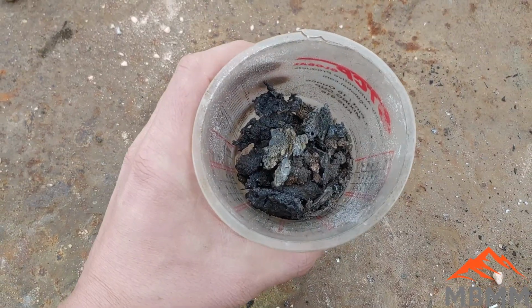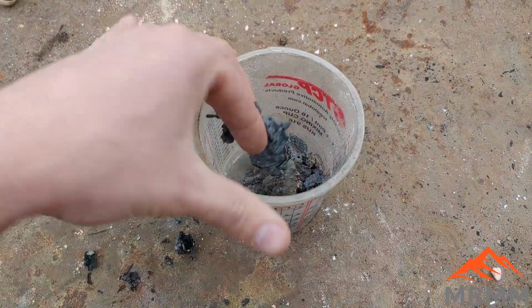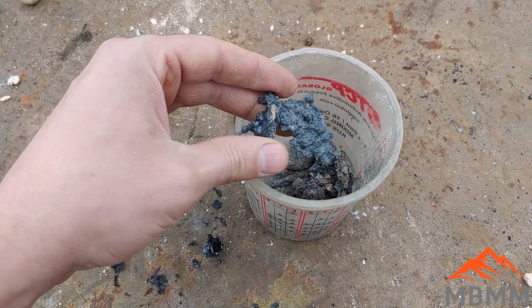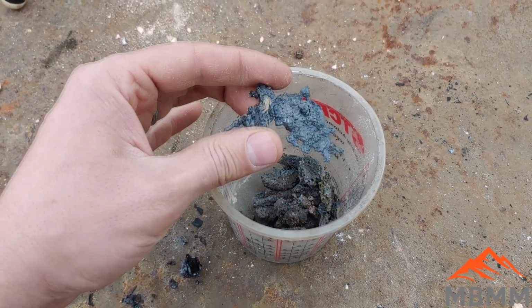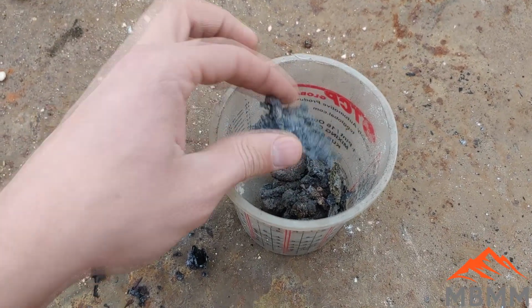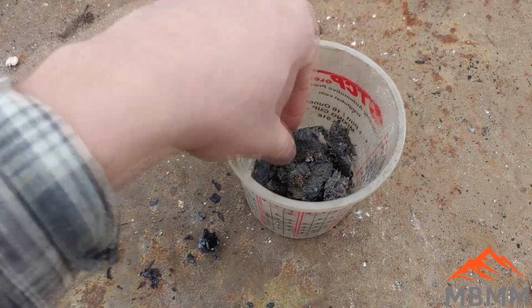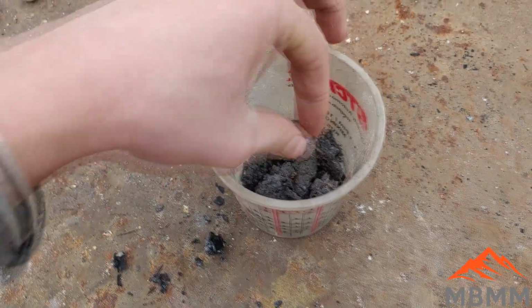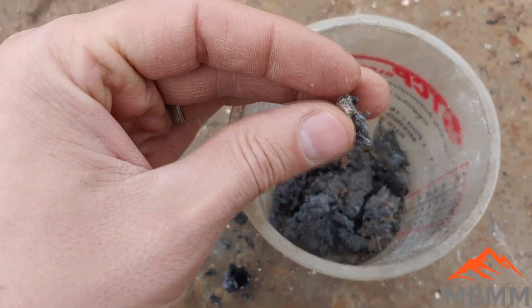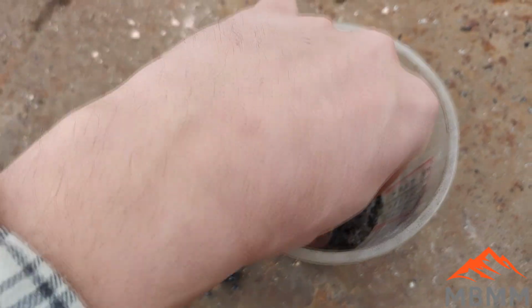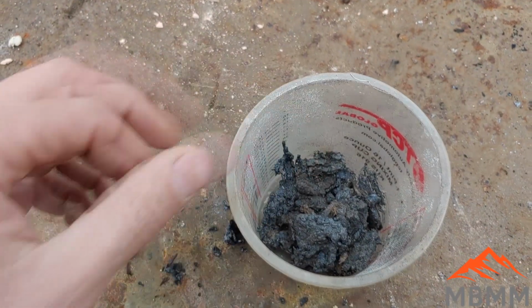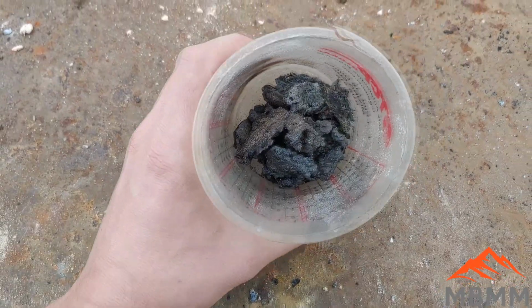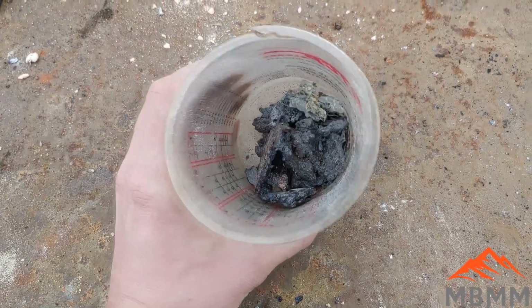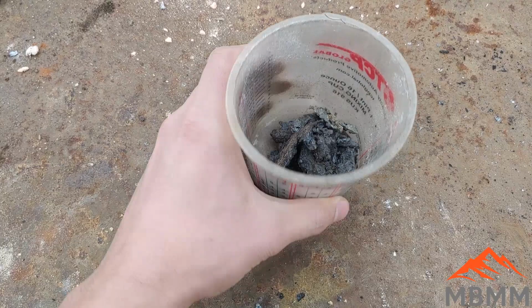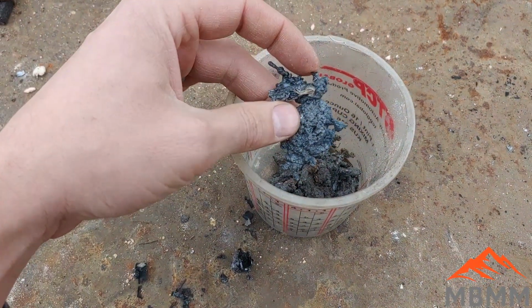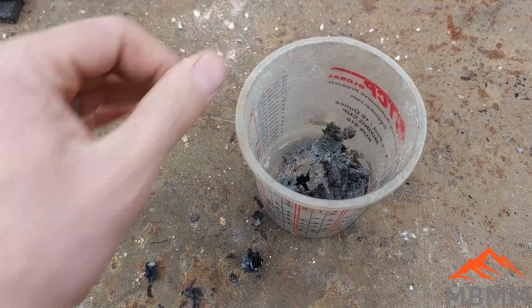But I've got about 300 grams of iron oxide here mostly. And what I'm going to try and do is smelt this now, because hopefully all the iron's oxidized. I'm going to use some borax and a little crucible, because you might be able to see on this piece, there's still little silver beads caught up in there. I don't think there's much. There's probably more stuck on that cupel than is in here. But just to be thorough, and I'm curious, I want to see how much silver is stuck in this iron oxide that I scraped off. So we'll get that going.